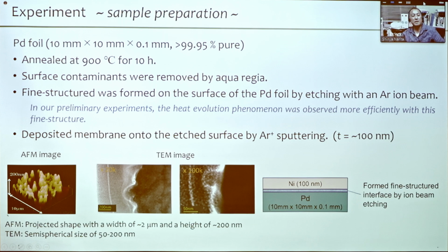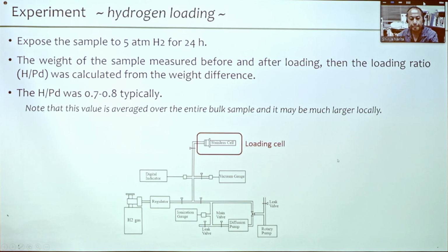So in a preliminary experiment, the heat evolution phenomena was observed more efficiently with this fine structure. So in our previous experiments, we tested the sample without this fine structure, but this fine shape seems to be effective. Then after that, nickel membrane was deposited on the surface. So this is a sample structure. And then hydrogen loading.